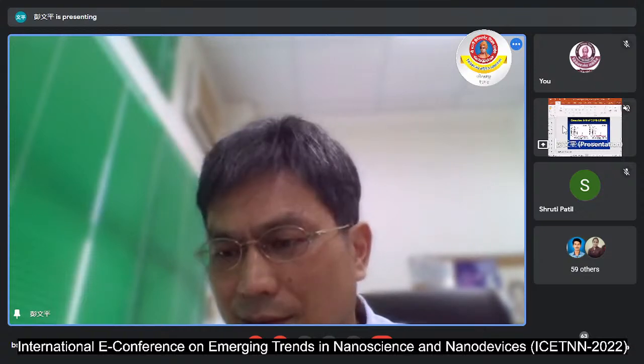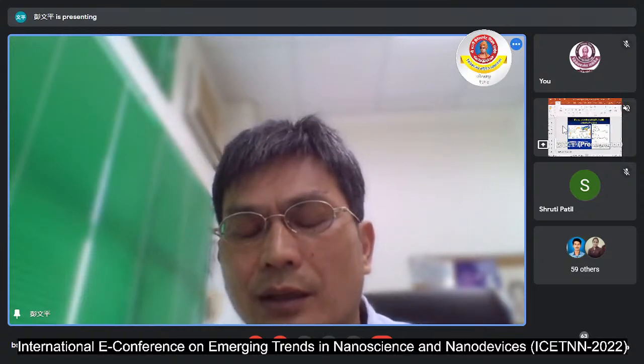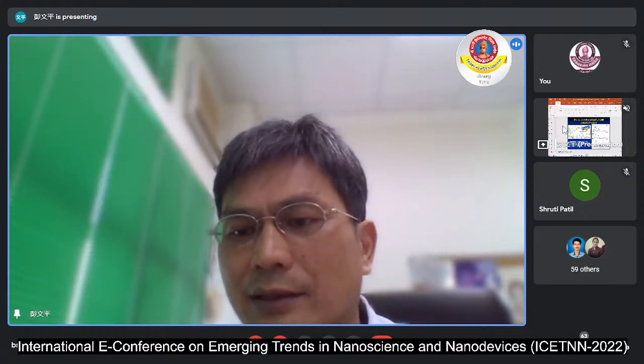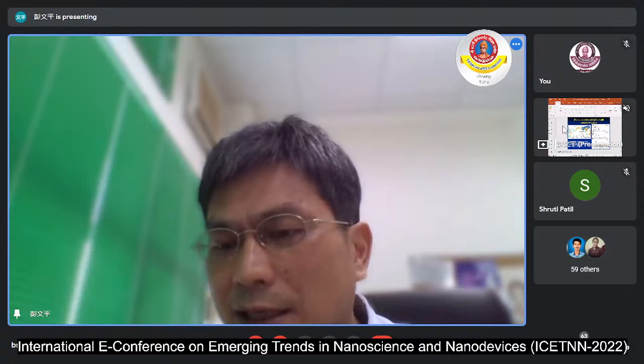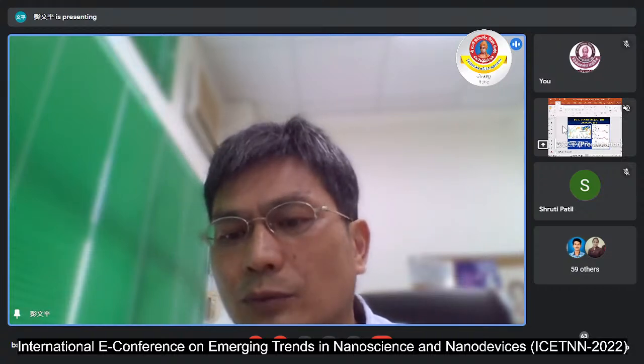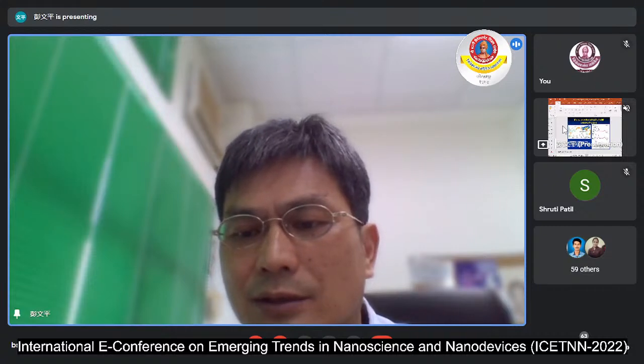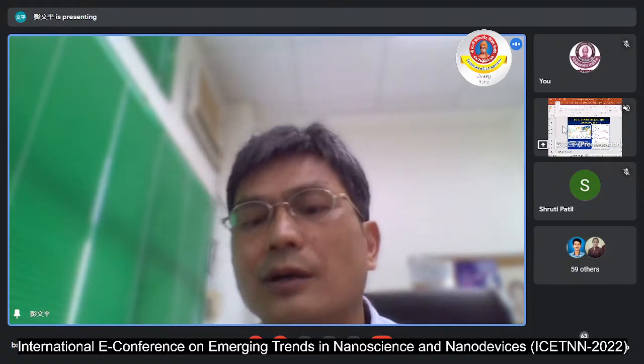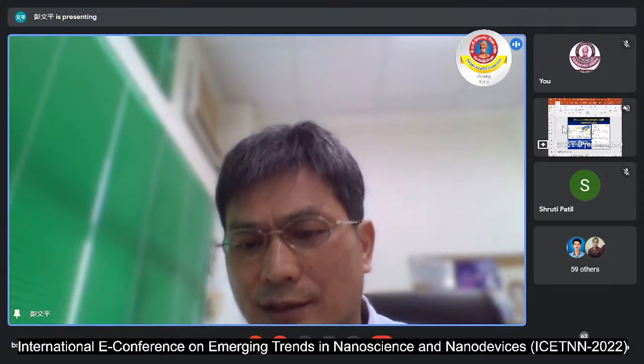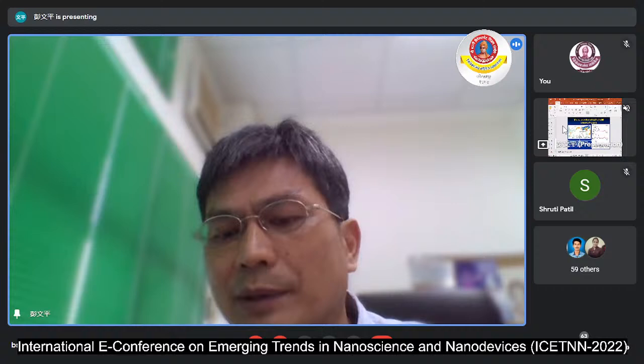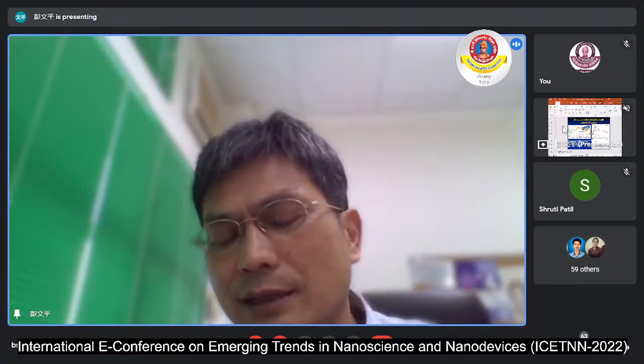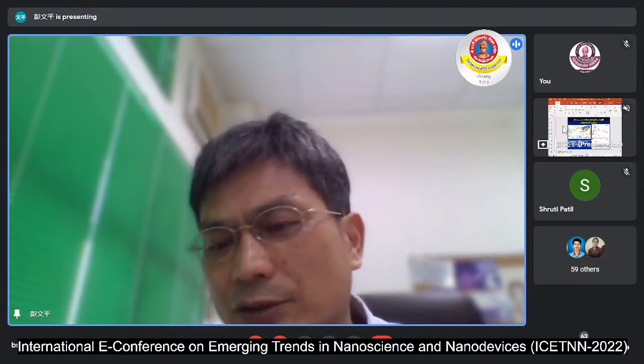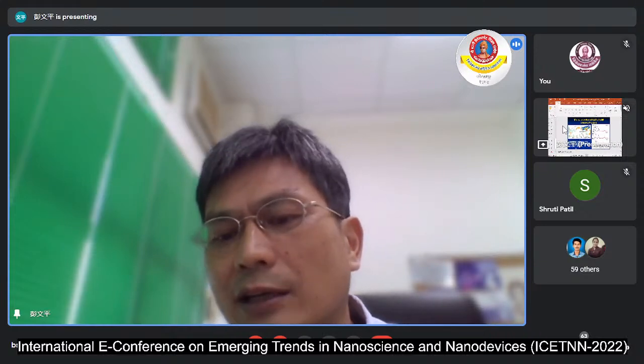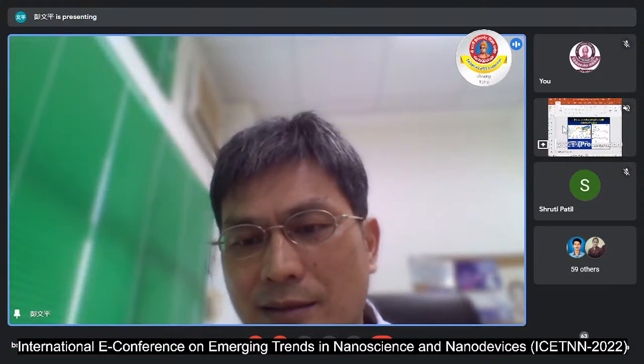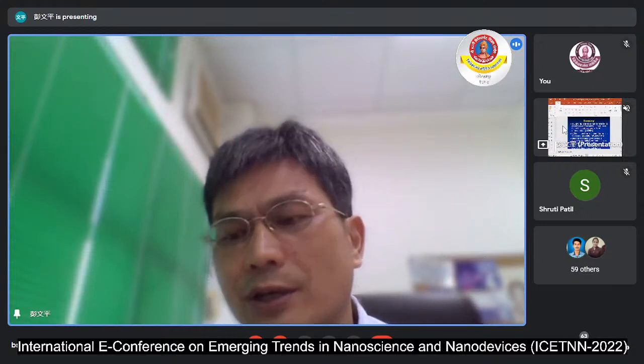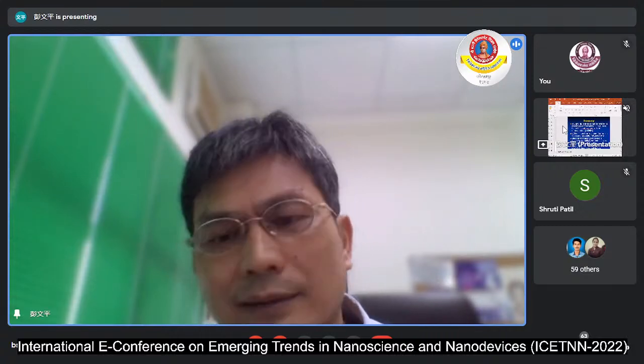And with the use of the nanodiamond here, we found we can even enhance the signal, even down to 5 nanomolar. So the single charge signal is not invisible, but we can see double charge, okay, third charge, fourth charge, and fifth charge. So that means our methodology is quite sensitive and can be better than other techniques. For example, people use a long fiber detection technique, and they can detect around 10 nanomolar, and we can be better than that. That's quite impressive also. So I think time is almost done, 30 minutes.